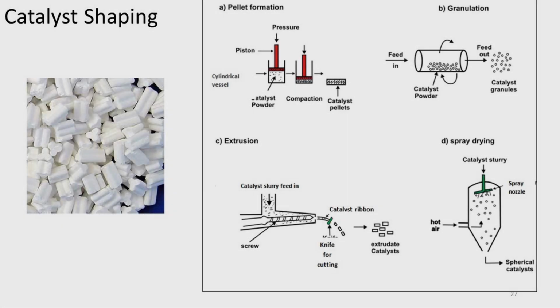Extrusion is the most widely used technique for the shaping of fixed bed catalysts or carriers. The principle looks simple. A highly filled suspension or paste is passed through profile channels that determine the shape. A high pressure may be required for transport and deformation of this paste, but other than in pelleting, the effect of extrusion pressure is smaller. One of the great advantages of extrusion is the flexibility with respect to the porosity of the finished product. Through adjustment of the liquid-solid ratio in the extrusion paste, it is possible to vary the porosity between about 30 and 60%.